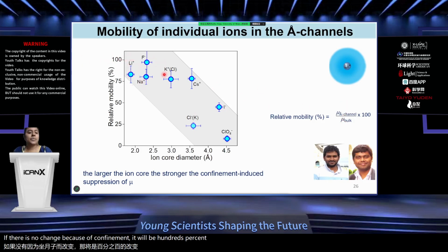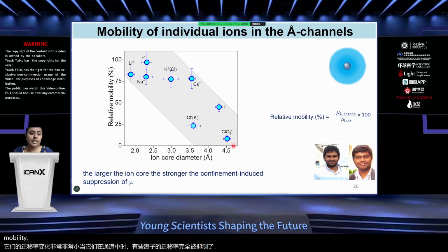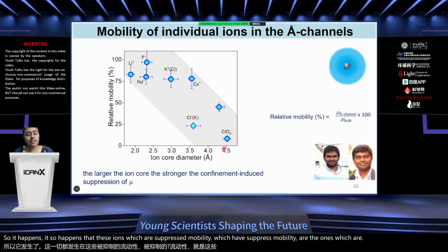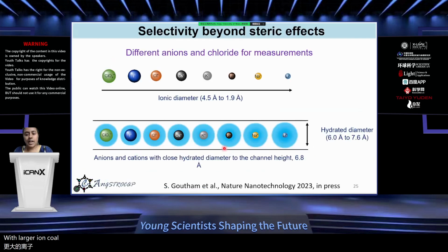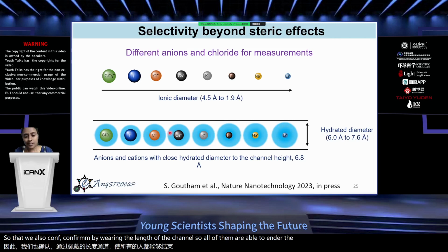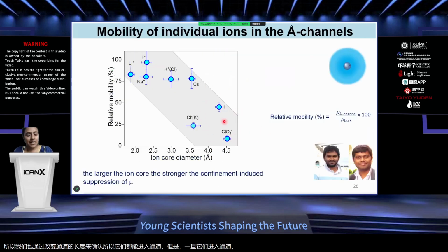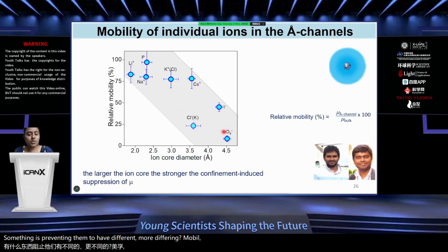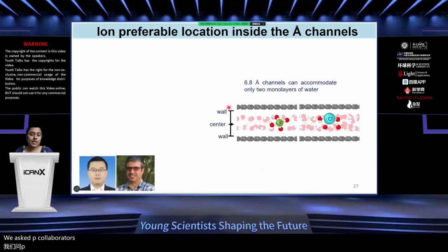So there are some ions which have no change in their mobility, or very small change in their mobility when they are in the channel, and there are ions which have completely suppressed mobility. It so happens that these ions which have suppressed mobility are the ones with larger ion core. Just to remember, there is no resistance for these ions to enter. That we also confirmed by varying the length of the channel. So all of them are able to enter the channels, but once they enter, something is preventing them from having similar mobilities.